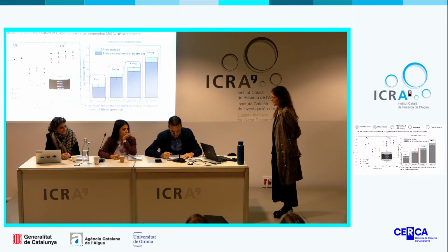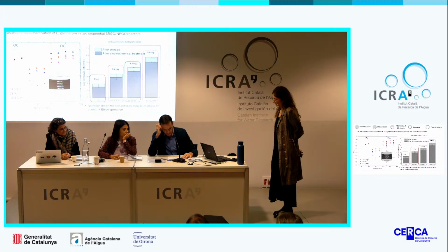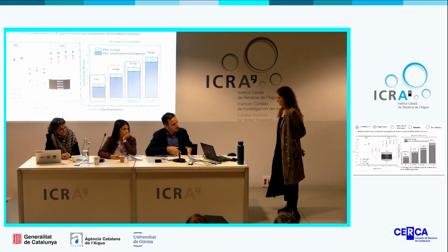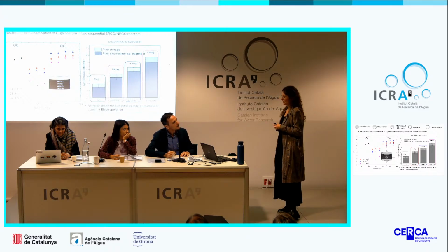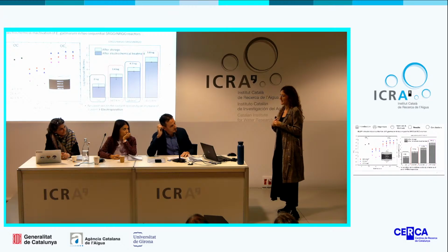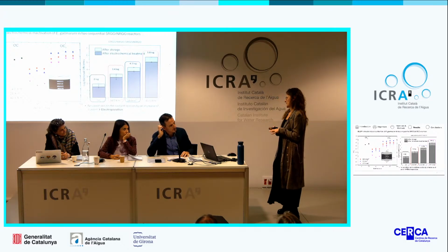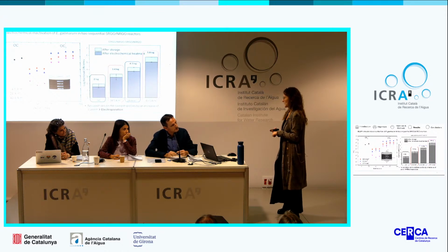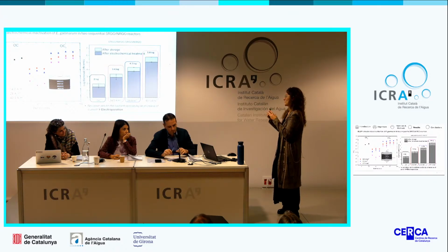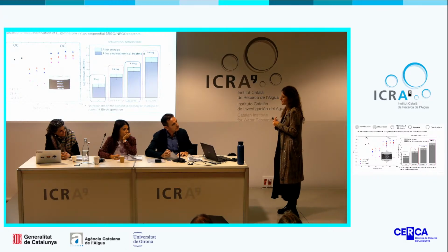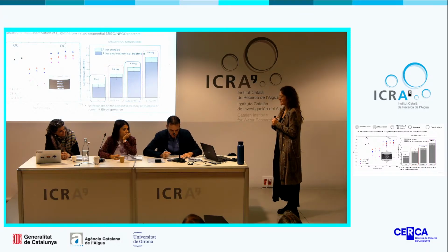Yeah. I have some quick questions to finish. I don't understand very well in the synthesis procedure of the reduced graphene oxide, how is it reduced? Which is the reductant? It's reduced in the hydrothermal treatment, because we are using an acidic solution of GO, and we soak the mineral wool in this solution, and through the temperature in the hydrothermal treatment, due to the high pressure and temperature, the GO is reduced to RGO. Without any reductant? No, we didn't add anything. Okay.